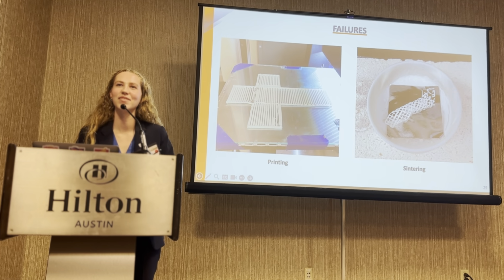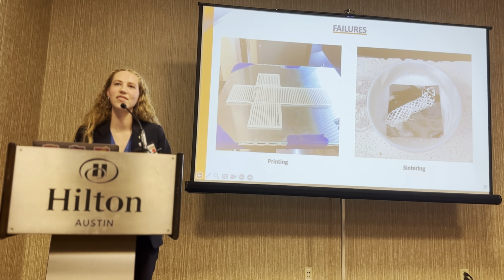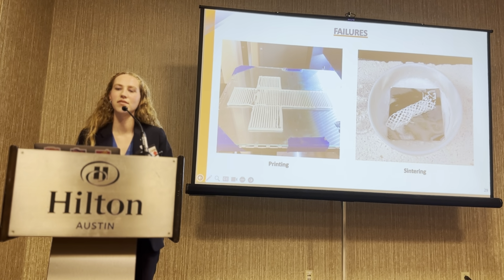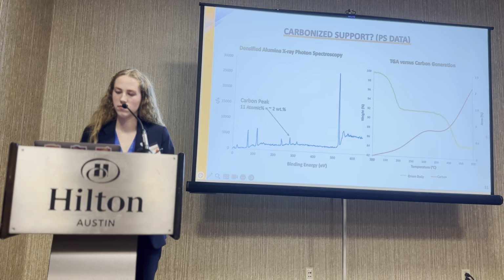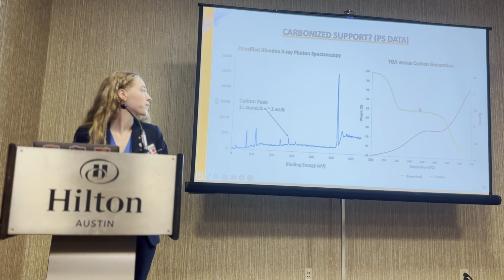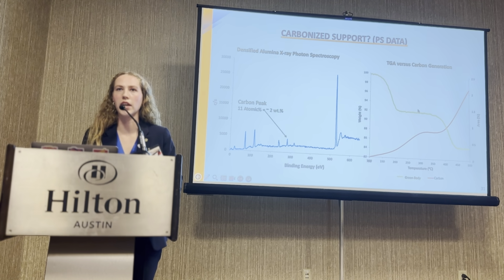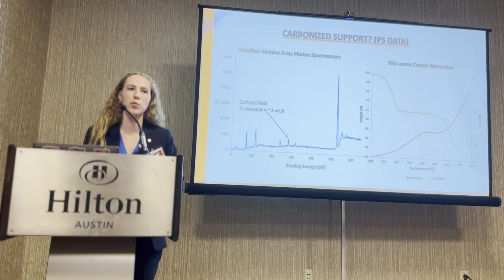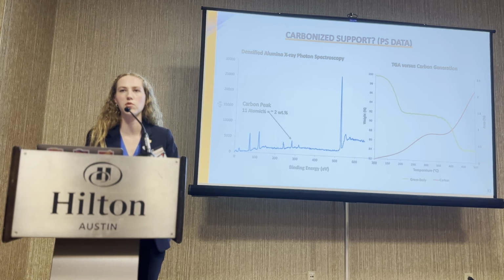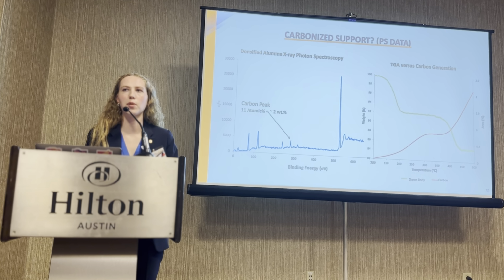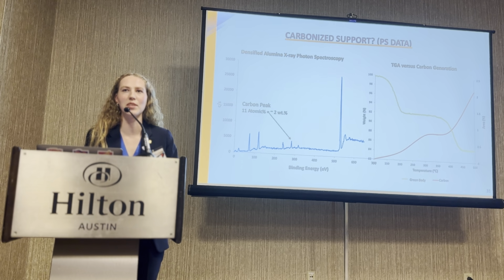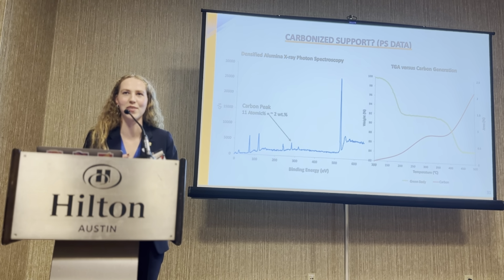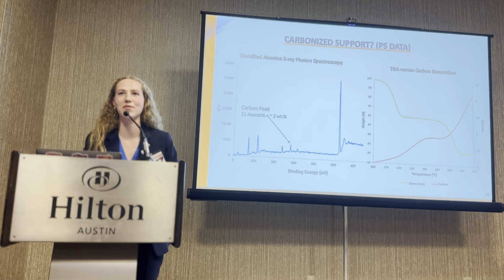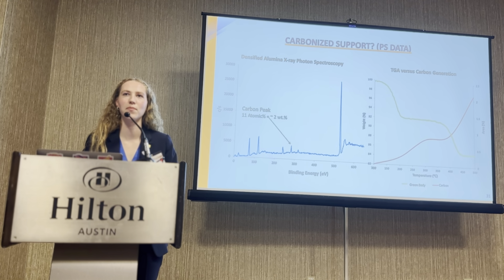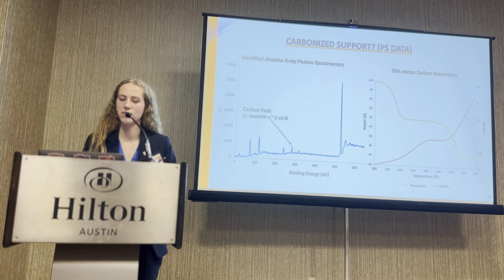Two quick questions. What happens to the carbon in the burnout? What happens to the carbon from the center? So the carbon during sintering creates that lattice structure, which enables it to maintain the shape without external support. If your question is whether it's just an alumina and carbon structure after sintering, the carbon does eventually burn out, as carbon monoxide or carbon dioxide or something.